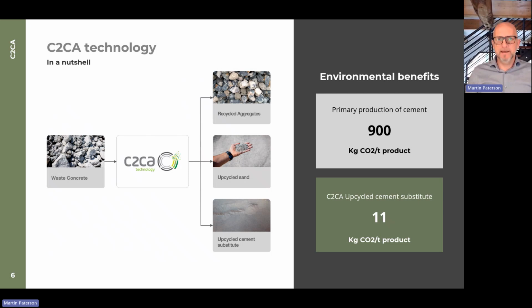What are we doing in C2CA again? In a nutshell, we have waste concrete, we put it into our process. Out of that, we get 3 main material streams: aggregates, sand, and a cementitious paste. And if you look at the latter one, the cementitious paste, after it's been activated in our process, and I will show you in a while how this looks, we have a third-party verified carbon footprint of only 11 kilograms CO2 per ton of product.